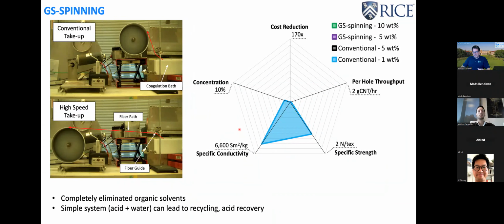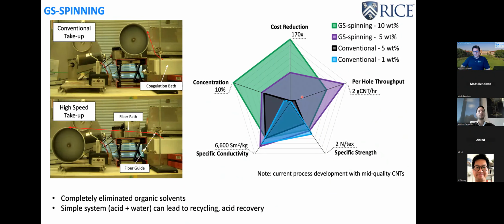And if you look at essentially efficiency, you want to go outwards in all of these characteristics. You want to have high properties, and then you want to have a high throughput of fibers, and you want to have the highest possible concentration of solids in your solvent. And we used to lose properties as we increased the concentration and throughput. And now we found ways to increase throughput and concentration and reduce cost while keeping the properties essentially the same. And this is also an area where there is a lot of work that needs to be done, and it has to be done in parallel with the synthesis because the two interact with each other.